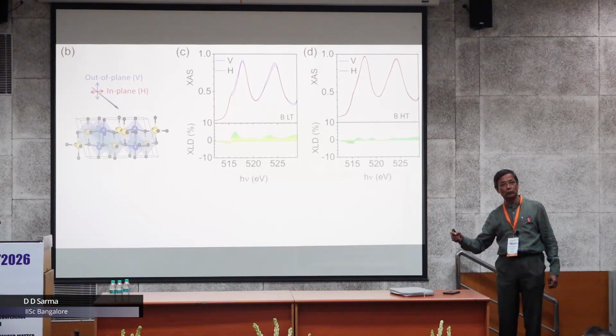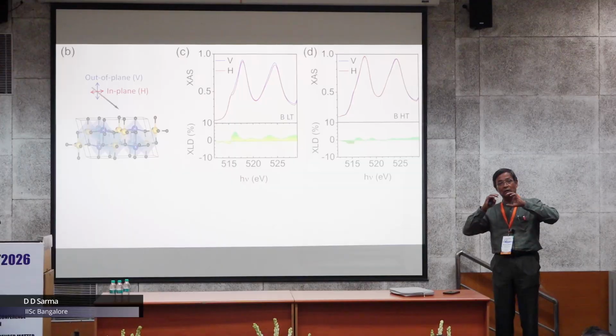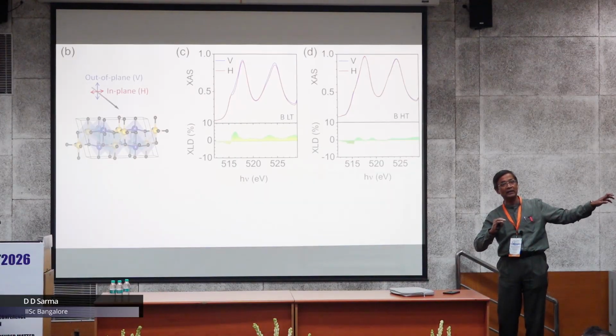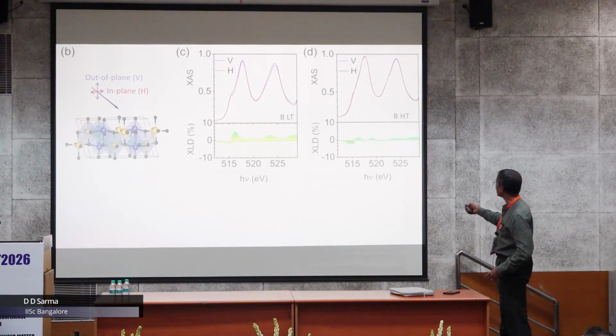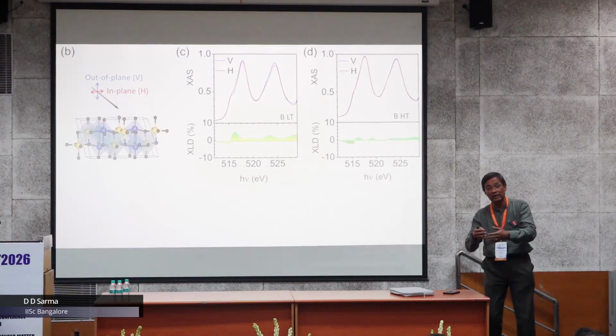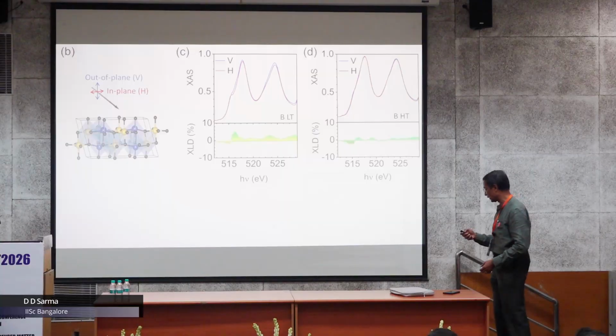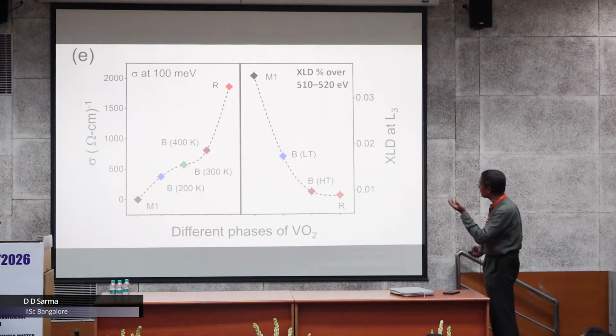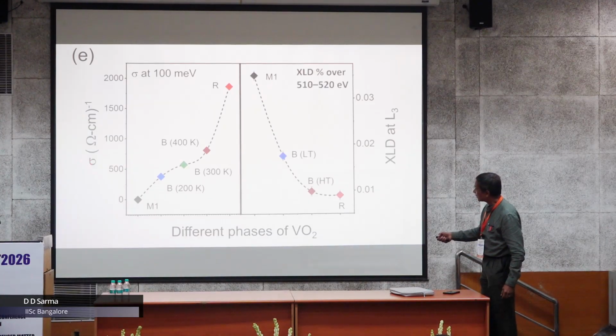Low temperature remains polarized. You have a sigma band that's almost completely filled with hardly any leaking out into other orbitals. But at high temperature, a large part of this sigma bond, the dimer level, hands over electrons to the other state. And this can be seen, there's a direct correlation with the optical conductivity.